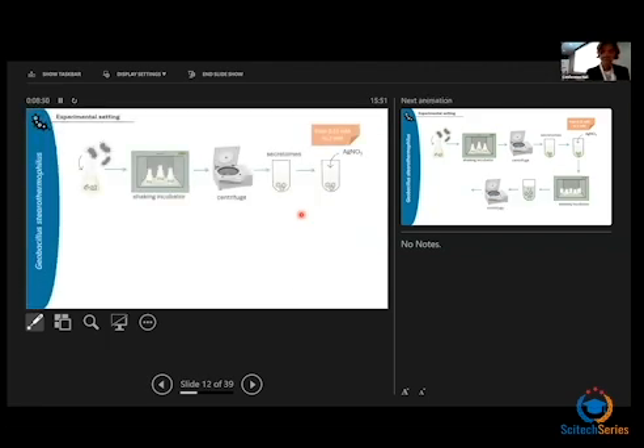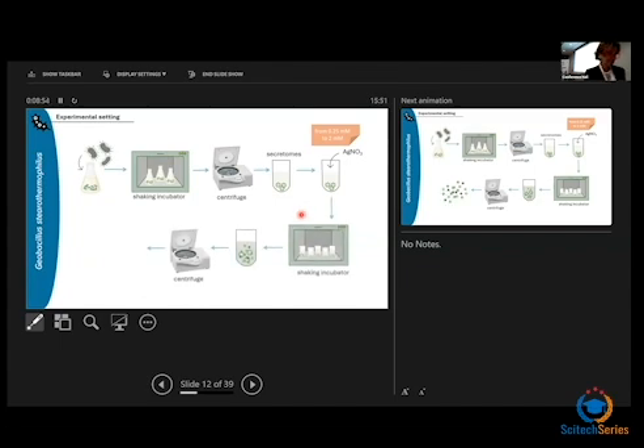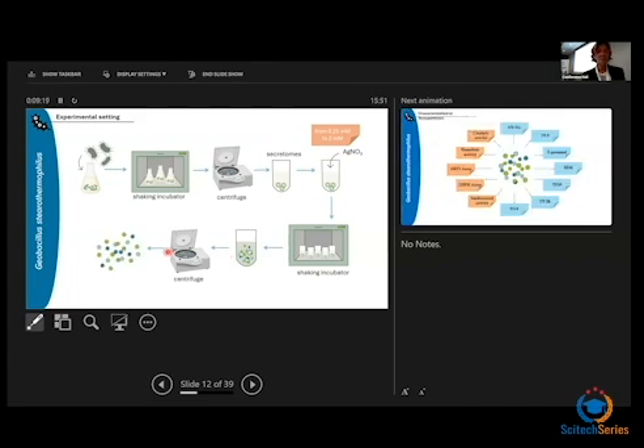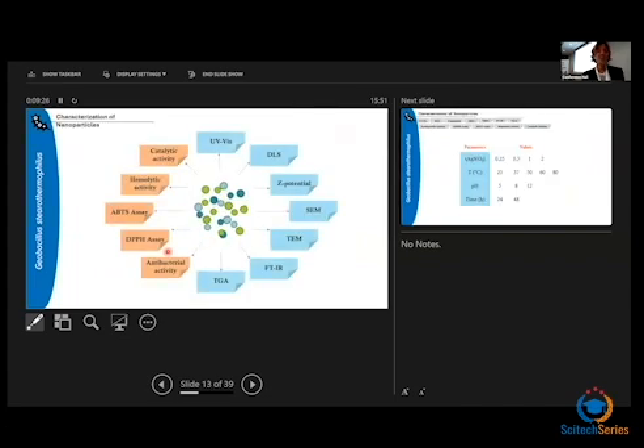In this slide, I'm showing the experimental setting, the protocol that we set up to assess the formation of silver nanoparticles. We started by growing the bacterium and then collecting the secretomes. To the secretome, we added different concentrations of silver nitrate, incubated for a while, and then recovered the nanoparticles by centrifugation. We made a thorough characterization of the nanoparticles with several techniques, and also assessed their biological properties with some studies that I'm showing in a while.